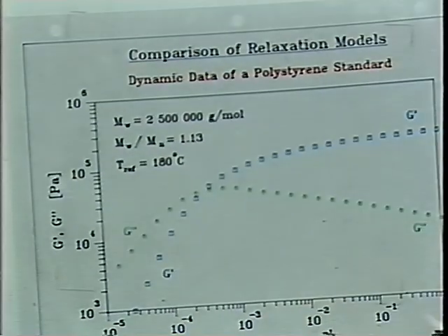So the Rouse model describes a material at about the critical or the characteristic molecular weight, or a polymer near the entanglement molecular weight. It's not long enough to form entanglements. So it goes from the flow regime, from regime 1, directly into regime 3. Okay? And that transition is performed actually quite nicely with the Rouse model. The slope here might be different for the glass, but still it's a very powerful way of doing that.